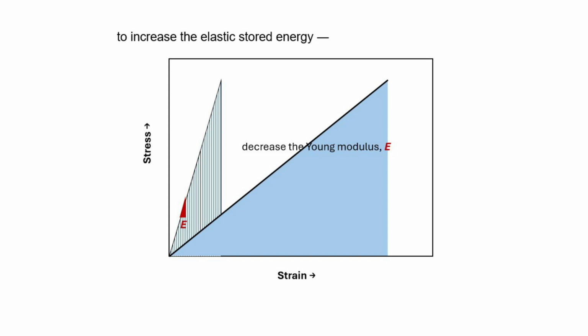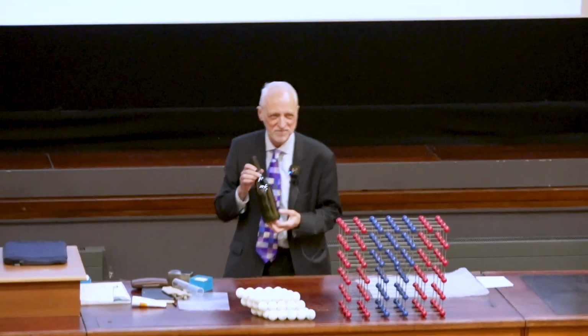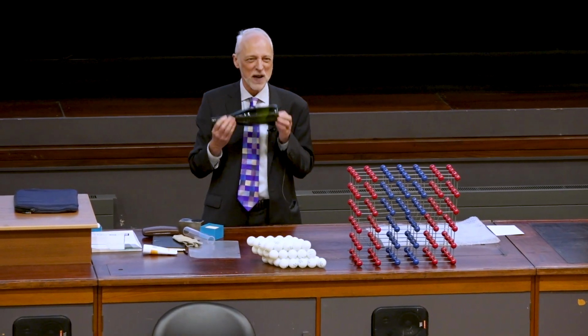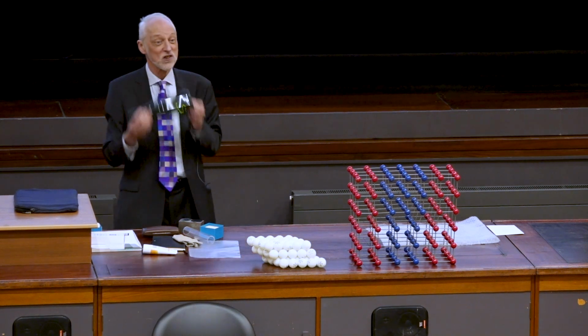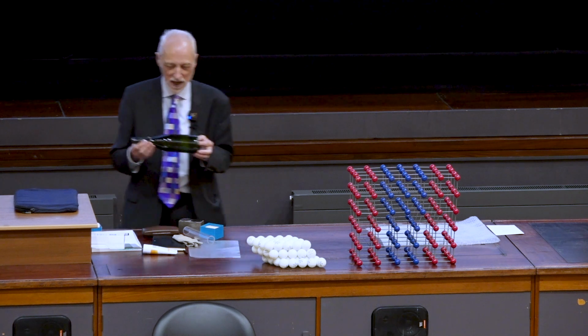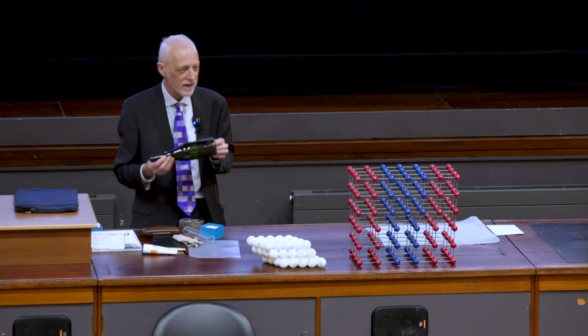So this is something underlying the behavior you just saw, that we can store more energy if the material is more resistant to plastic flow of those strains. You can simply go higher without making an indentation, and it helps that it also has a lower elastic stiffness. Now, so far that sounded pretty good, but there can be a bad aspect to it, and that is we think, well, if the flow of the material is too difficult, could it be that the behavior is really like conventional glass? After all, this is very hard. It's very scratch resistant. It's arguably quite strong. It doesn't flow easily at room temperature. But it does have a drawback. And the drawback, Gabriel will now demonstrate.